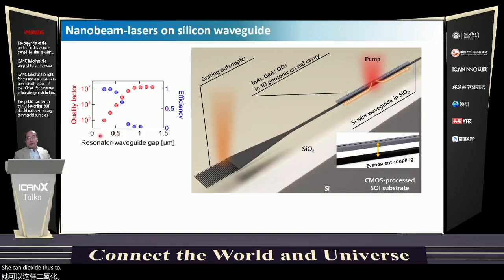There should be some optimum gap for realizing high quality factors and high efficiency coupling. If the gap is smaller, coupling efficiency can be improved. However, cavity quality factor is reduced, and so on. So therefore, there should be an optimum. The optimum gap is around 0.6 micron and so on.